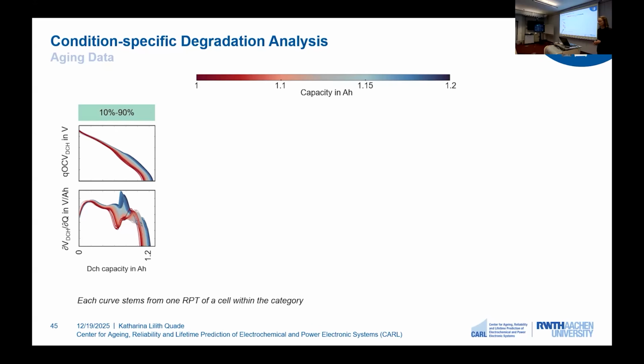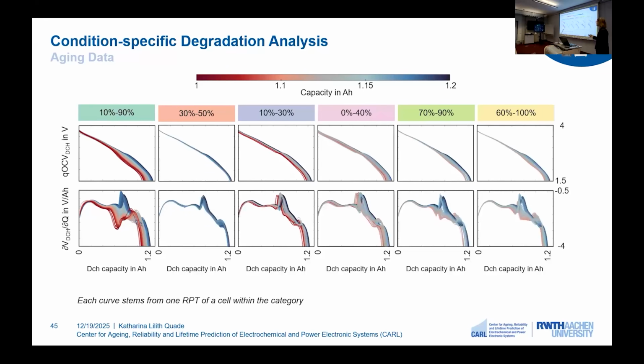This means for the condition 10% to 90% SOC, we cycle 40 cells, and let's assume we have on average 20 reference performance tests. So here we can see 800 curves. And the color of the curves corresponds to the capacity. And again, we do the same thing for all other categories, and we can see, honestly, a less clean picture. And this is because we have different degradation modes overlapping, because we have different aging phenomena overlapping. However, we still want to find out what is the main degradation mode per category.